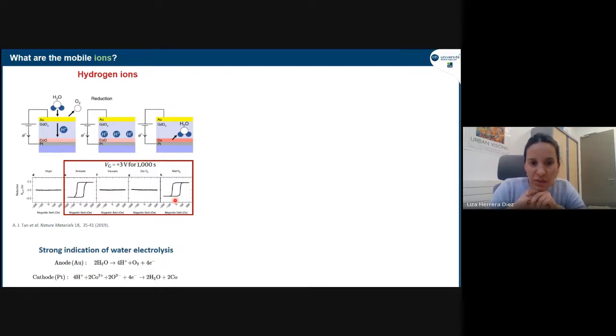So this was really one of the studies that pointed out quite clearly that there was a need to have water in the system. And this is something that, for example, in our case, we have seen with the tungsten system that I showed you before. I will go into detail later on, but this is a system we had to anneal before doing magneto-ionics. If we take it out of the oven and try to do magneto-ionics, it doesn't work that well. So we have to leave it for some time in air, and then if we do magneto-ionics after that, it will work. This is clearly an indication that the system is hydrating again after letting out all this water and oxygen during the annealing, and that it needs to get this back to have an efficient magneto-ionic response.